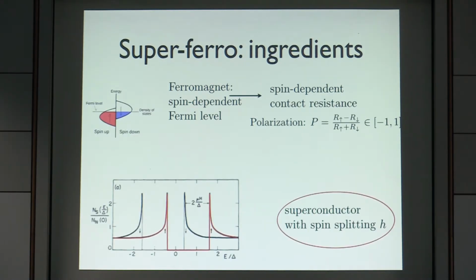Okay, so now let's go back to the superconductor-ferromagnet systems after this detour. In the ferromagnet, let's remember that we have this spin-split Fermi surface, which leads to a spin-polarized interface. This translates into the fact that whatever we are measuring at the interface, we should weigh spin up with a different weight than spin down. The other ingredient that I have here is the spin-split density of states of the superconductor carrying a finite exchange field.